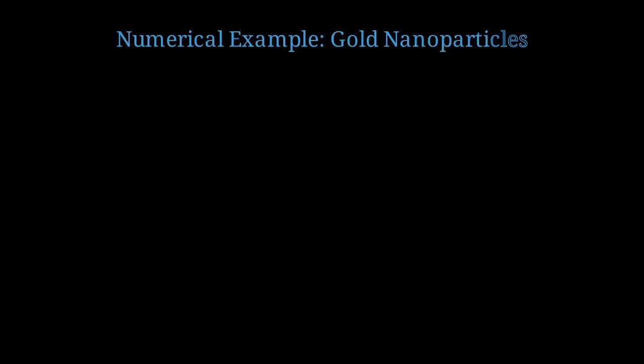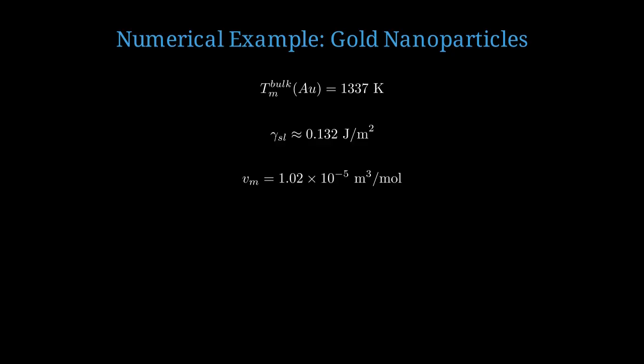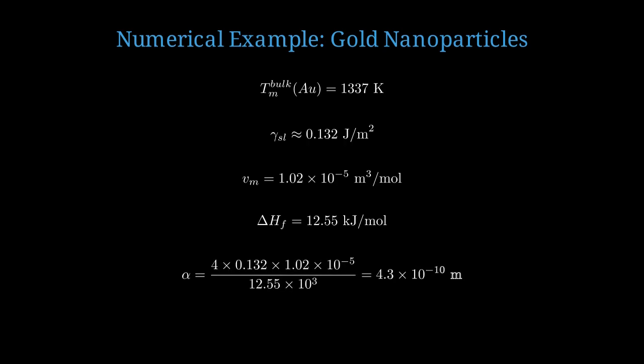Let's work through a concrete example with gold nanoparticles to see how significant this effect is. The bulk melting temperature of gold is 1337 Kelvin, which is 1064 degrees Celsius. The solid-liquid interfacial energy for gold is approximately 0.132 joules per square meter. The molar volume of gold is 1.02 times 10 to the negative 5 cubic meters per mole. The latent heat of fusion is 12.55 kilojoules per mole. When we calculate alpha, we get 4.3 times 10 to the negative 10 meters, or about 0.43 nanometers.